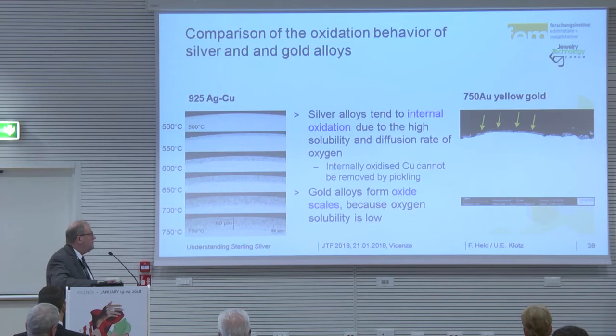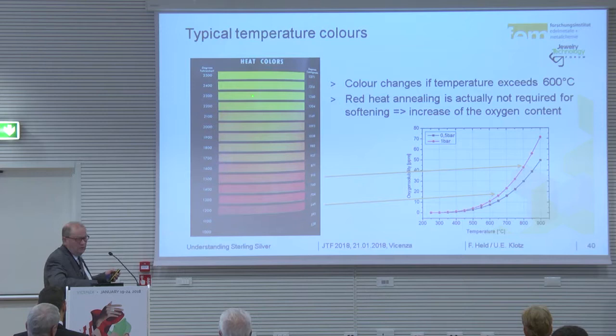That's for the goldsmiths, only typical temperatures, colors, and here oxidation, solubility of oxygen in silver. You see, if you make it with low temperature, you are low. If you increase temperature, you really have a lot of oxygen in your material.